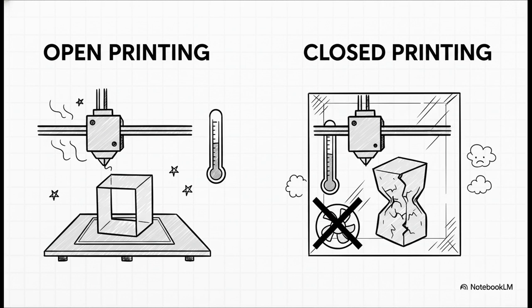ABS absolutely requires a closed printing environment with the fan completely off. If you cool ABS too fast, the rapid temperature drop will cause your print to dramatically shrink and crack, and nobody wants that during an evaluation.